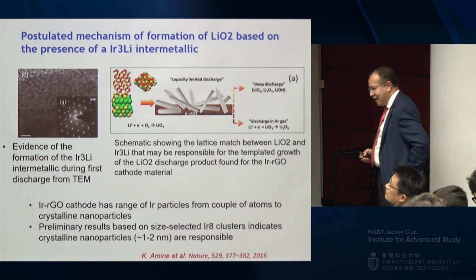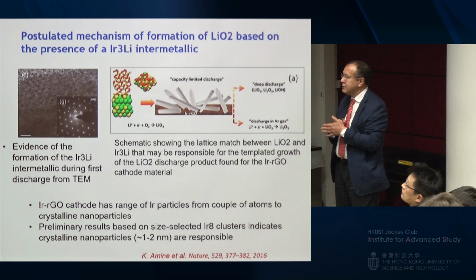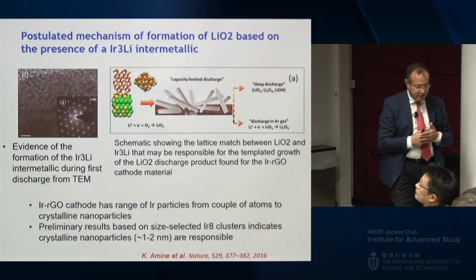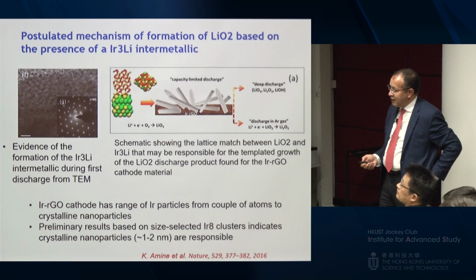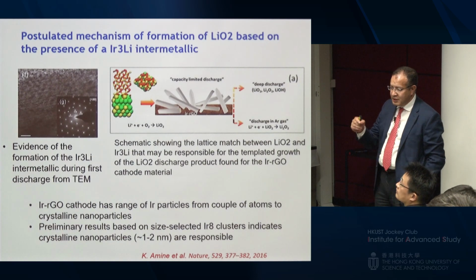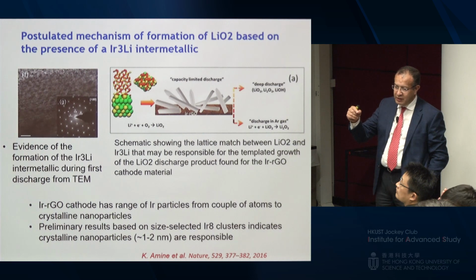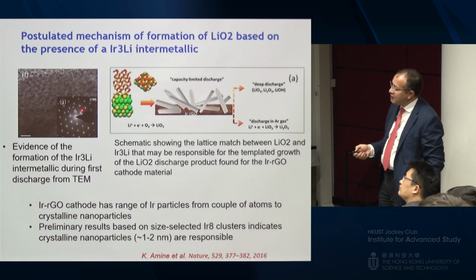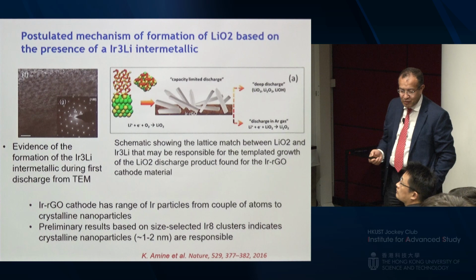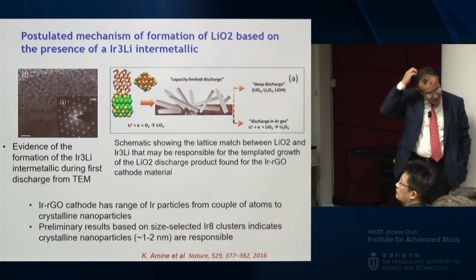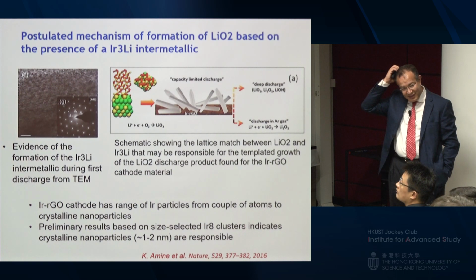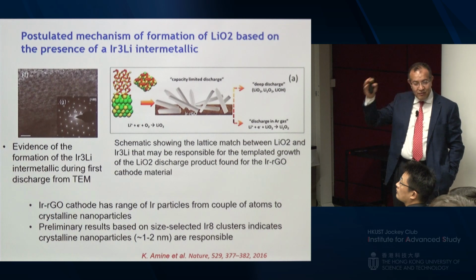So how did that happen? What is the reason why the superoxide, lithium superoxide, is stabilized? So we went back and looked at these electrodes, because we've seen most of them are in proximity of the catalyst. And we looked at the catalyst itself, it changed. It became iridium-3 lithium. So there is a reaction. The catalyst actually changed in situ during the initial cycling. We have a different catalyst.